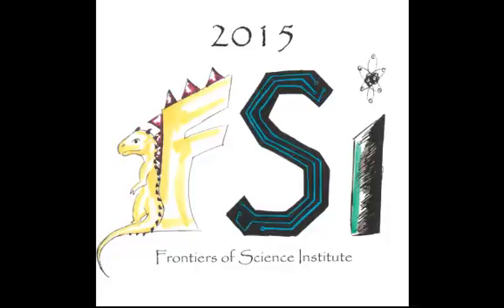Graphite has a hexagonal crystal structure, which gives it a Mohs hardness value of about 1 to 2, quite different from diamond. What we're more interested in is graphene. Graphite is made out of sheets of graphene. This here would be 1 sheet of graphene, if you can imagine it extending out as far as it needed to. The graphene sheets are stacked on top of each other to make graphite, held together by van der Waals forces.